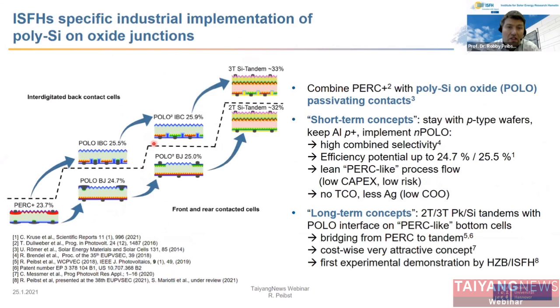And now let's come to the industrial implementation of these polysilicon oxide junctions. And here ISFH has developed a very distinct roadmap, which has a starting point from the PERC technology, or PERC+ technology, as we call it, in the bifacial version, where the aluminum is printed as fingers on the rear. And then we would like to combine our background knowledge from PERC+ with the polysilicon and oxide junctions, but in the first step keeping the wafer polarity as p-type, and in particular keeping the hole contacts, the selective contacts for hole extraction, with the aluminum-alloyed P+ contacts.